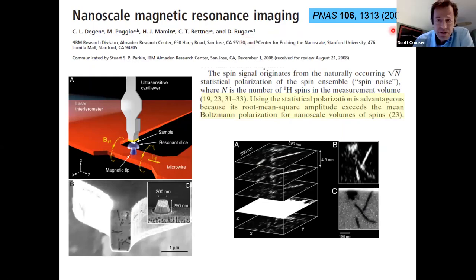In this measurement, which was reported, again, this is one of my very favorite papers. This was in the group of Dan Rugar. Just to give an example of how far people are taking this, using an incredibly sensitive magnetometer based, in this case, on a cantilever, the details aren't important. This group was able to image a nanoscale object. So in this case, they did an MRI of a single tobacco mosaic virus, right? And the key point here is that to get these tiny signals, they used the naturally occurring square root of N statistical polarization, or this spin noise.